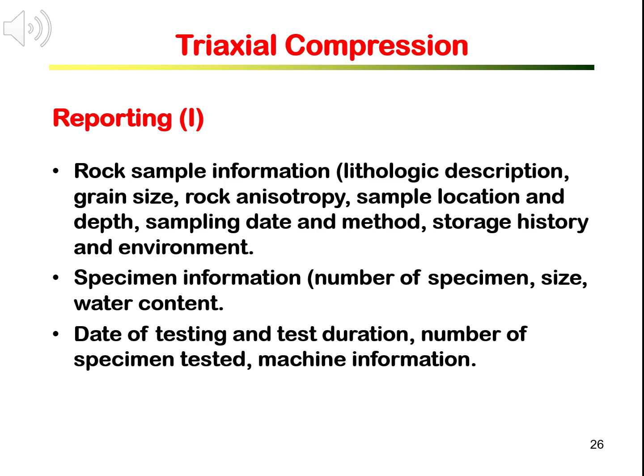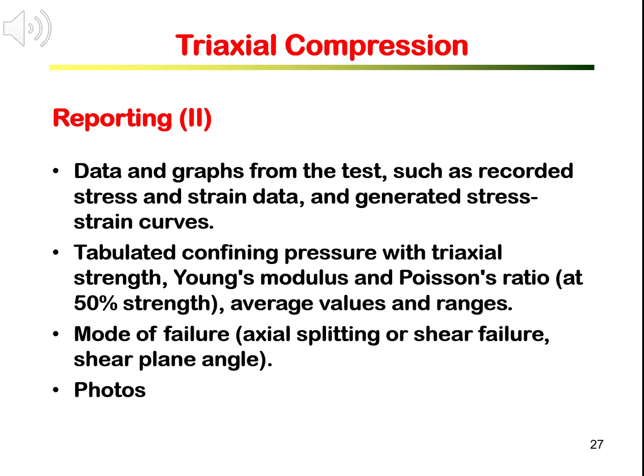C. Test date and duration, number of specimens tested, machine information, testing procedure, including descriptions of axial stress and confining pressure loading procedure and control. D. Data and graphs from the tests, such as recorded stress and strain data, and stress strain curves generated or plotted by the computer from the recorded data. E. Tabulated results on triaxial strengths, Young's modulus, and the Poisson ratio, generally at 50% of the strengths, with confining pressure, including average values and ranges.